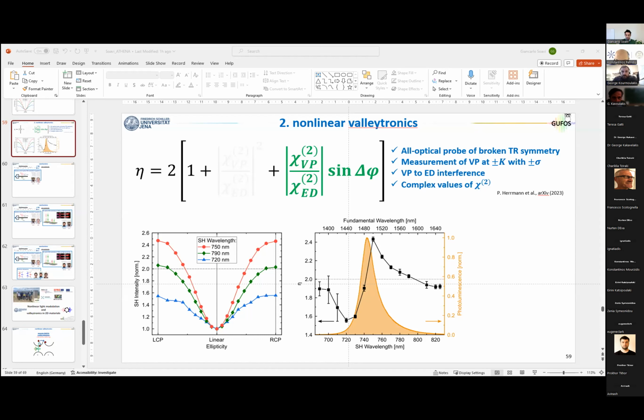So that's a very good point. To be fully honest, we still don't know. It's something that we still have to investigate. However, what I can mention is that, as I said, the shape that we read here is the interference between the intrinsic response, so let's say the imaginary part. So we can do the following. We can assume that the electric dipole response, so the response coming from broken space inversion symmetry, is mainly imaginary, because we know that when we are close to a resonance, the refractive index becomes almost purely imaginary. And this will be similar to the derivative of the absorption.